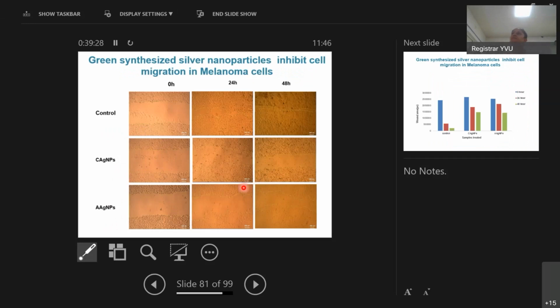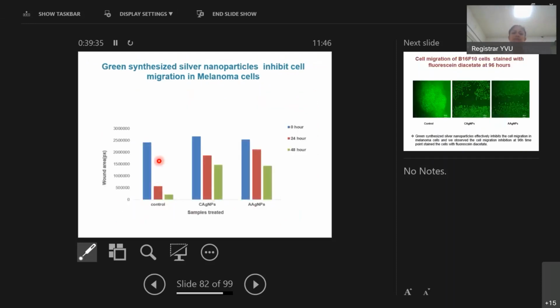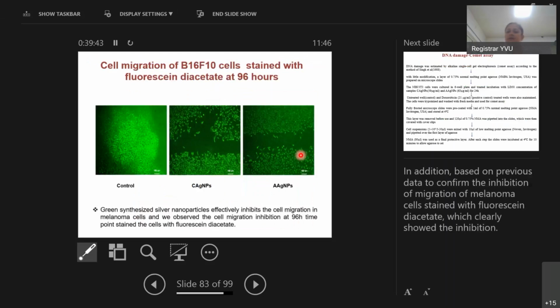Cell migration inhibition was seen at 24 hours and 48 hours. This is the wound area measured for cell migration of green synthesized silver nanoparticles in melanoma cell lines at 0 hours, 24 hours, and 48 hours. In addition, based on previous data confirming the inhibition of migration in melanoma cells, we stained the cells with fluorescein diacetate, which clearly showed the inhibition at 96 hours.